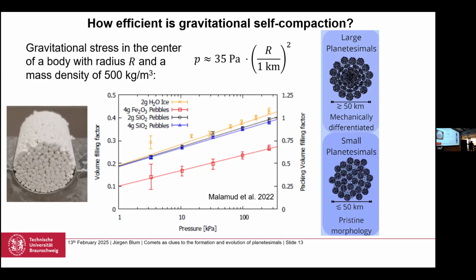And the result is that at some point, this stress here, this compaction is so high that we are starting to lose the individual pebbles. So a pebble pile where even in the center you can identify the original pebbles can only exist if the diameter of the body is smaller or about 50 kilometers. For all larger bodies, the center is so compacted that they forgot about their pebble origin. So if we want to find out whether this whole model is correct, so whether planetesimals form out of clumps of pebbles, then we should not look at those large bodies, but rather at small bodies. But 50 kilometers is a good size already.